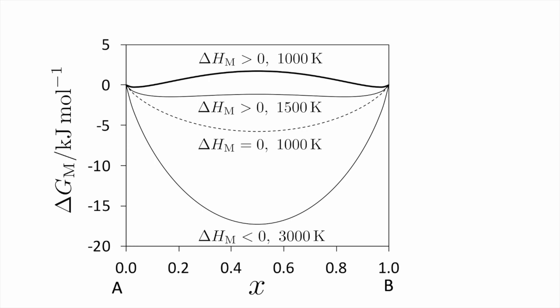So I've plotted some curves here for the free energy of mixing in a regular solution. That means where the enthalpy of mixing is finite. So we're plotting the free energy of mixing versus the concentration of B. If there was no enthalpy of mixing, we would get the ideal solution curve here with a minimum at 0.5 of B. And if the enthalpy of mixing favors the formation of AB bonds, then it will be less than zero, and we will get a much deeper minimum, again favoring the formation of near neighbor pairs which are unlike atoms. So you can see that if the atoms prefer to be next to unlike atoms, then we get a deeper minimum compared with the ideal solution.